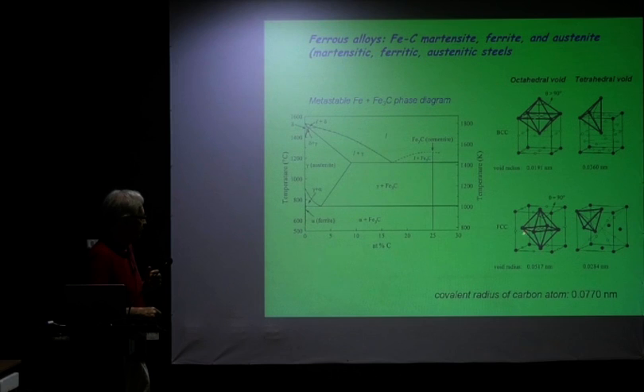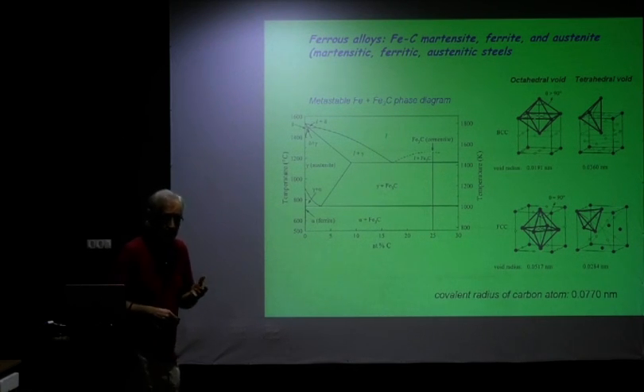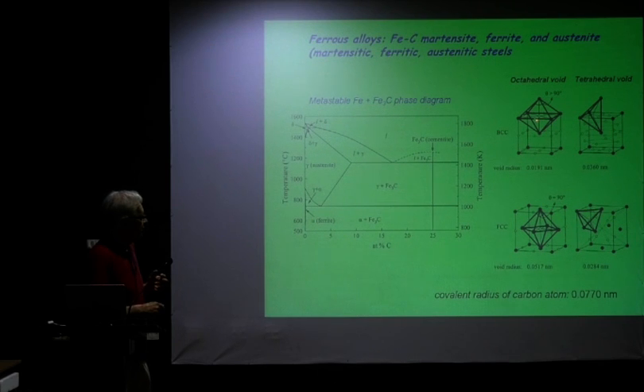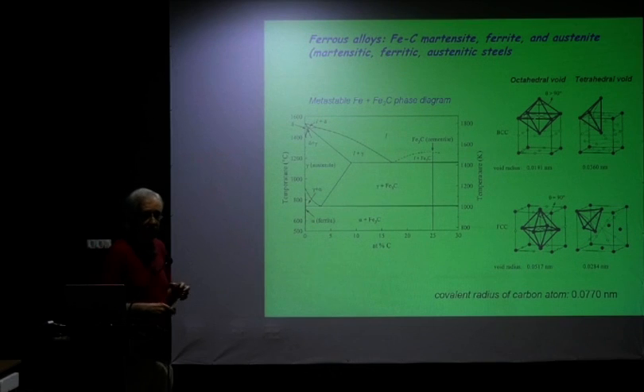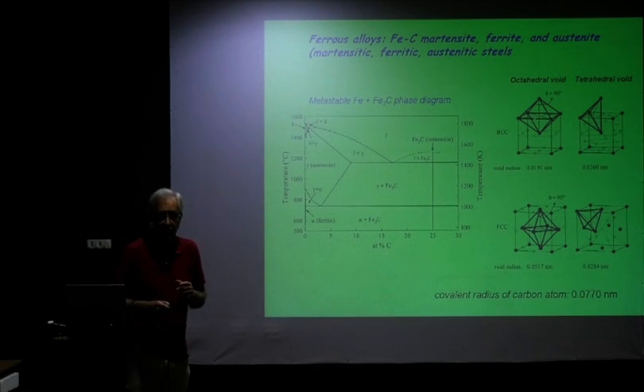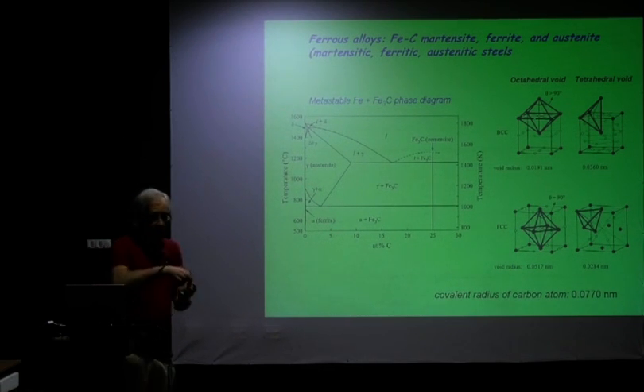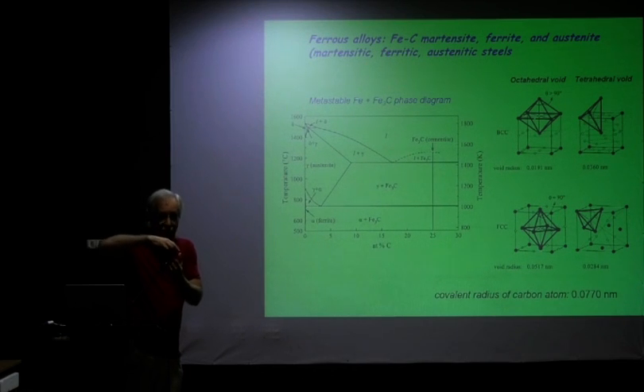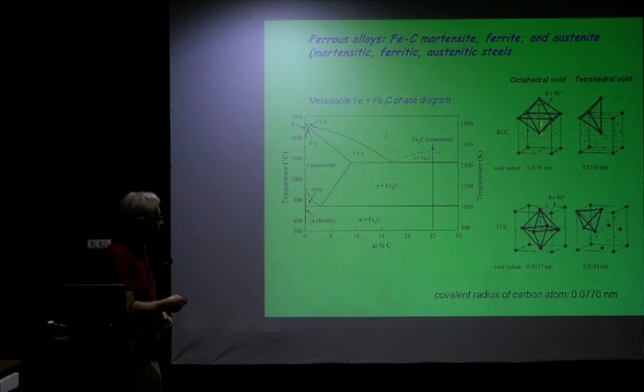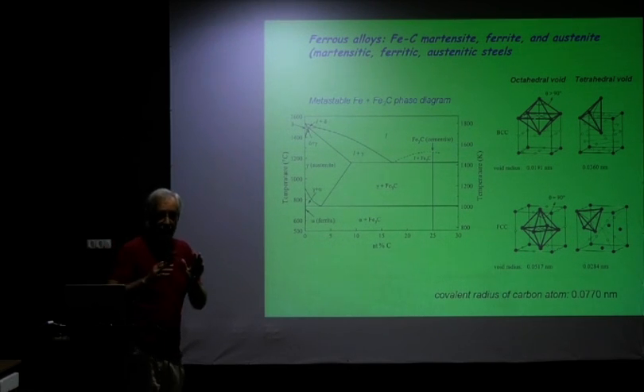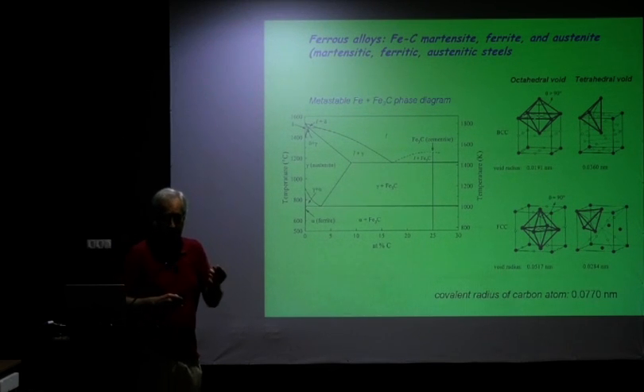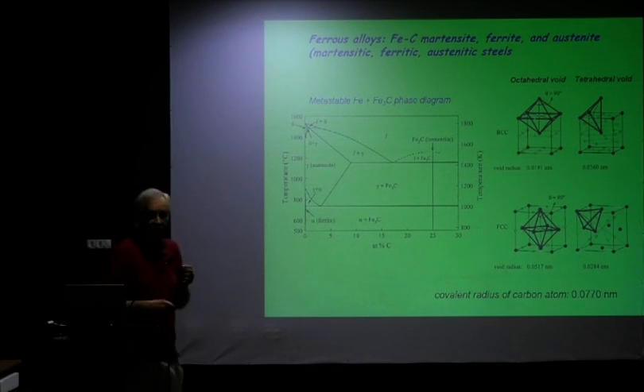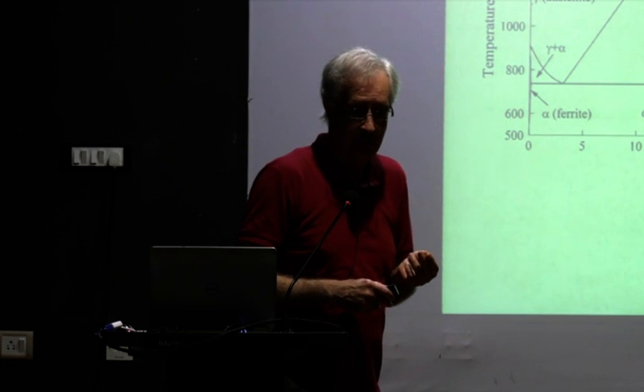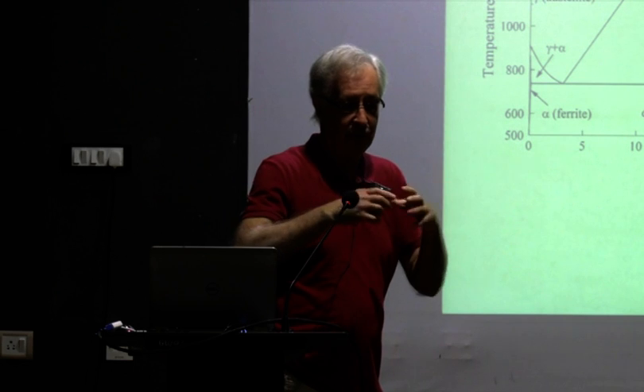So the same thing goes for FCC iron. We see that we have a void radius, which is also smaller than the carbon covalent radius. Now, in this case, it can either go in here or it can go in here. If it were to go in here, it has to expand everything in all directions, which costs a lot of energy. So instead of doing that, if we put carbon in here, then it induces a strain in this direction here, that's in the vertical direction, so that it distorts the lattice. And when we put carbon in there, we have a body-centered tetragonal state. And the body-centered tetragonal state is nothing but the martensite. Okay? So that's how carbon goes in there, by forcing its way in at high temperatures when you've expanded the lattice, and you get the martensite.